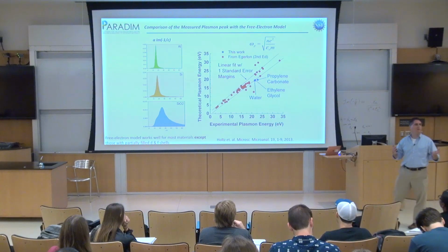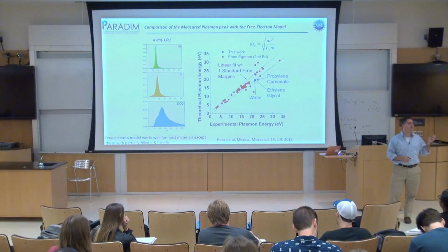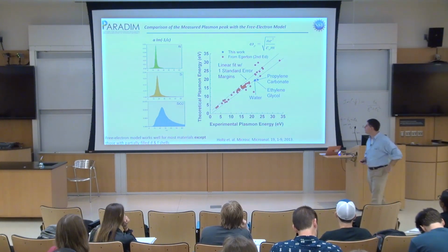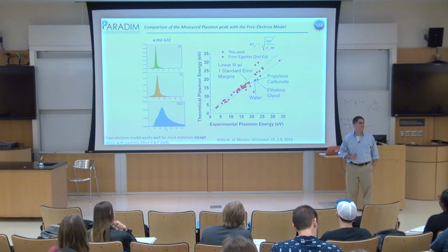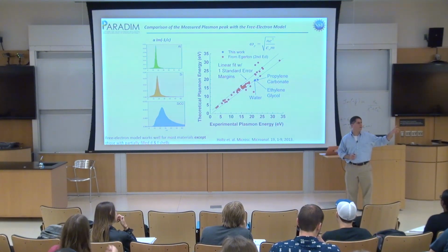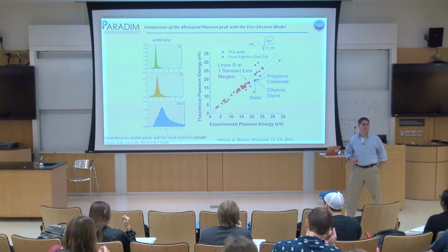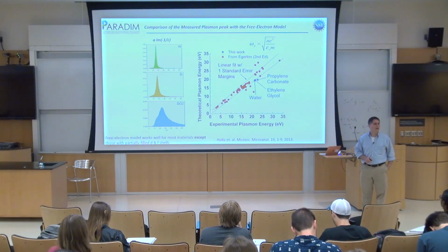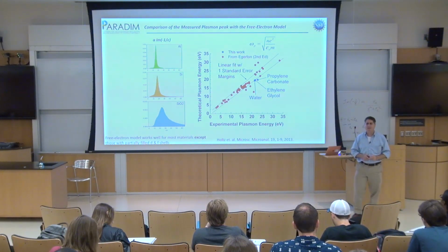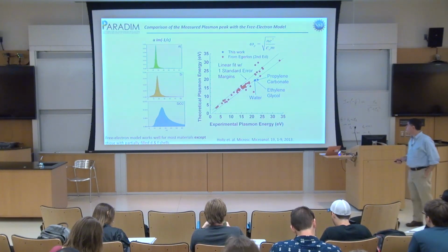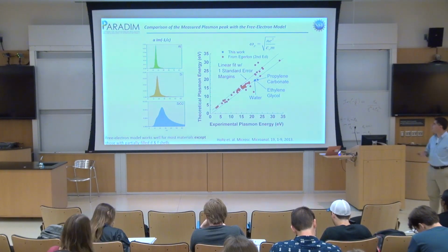It works well for materials that are kind of free electron-ish, and it works very badly for things with tightly bound electrons. So if you actually looked at the optical spectrum of nickel or cobalt or iron, you wouldn't be able to recognize the plasma frequency because there are too many single particle d-to-f transitions happening in the same energy range. So partially filled d and f shells mess up this analysis completely. And so platinum, people go, hey, platinum has a nice big plasma frequency. It's like, no, that's not a plasma frequency. That's a single particle transition. But for the materials that are not those things, this is a great way to guess the density.